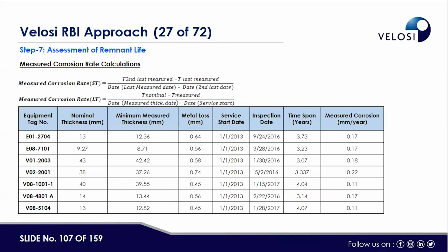The measured corrosion rate, how we calculate it, is from the second last measured thickness and the last measured thickness, and the dates. There are T nominal and T measured, and the other measures are short-term corrosion rate and long-term corrosion rate. Short term is between two inspections, this inspection and the last inspection, whereas long term uses T nominal at the original stage and T measured when we are inspecting, and the time in between.